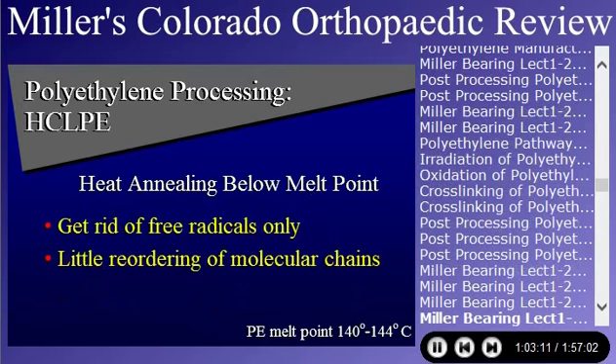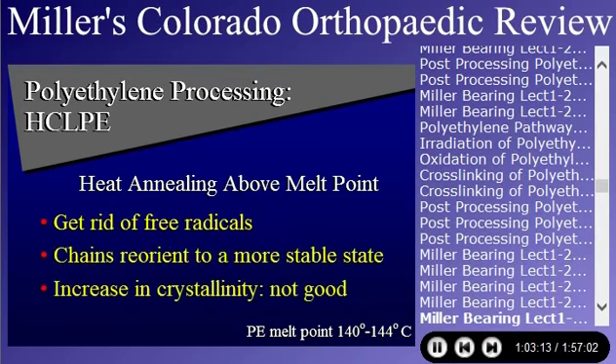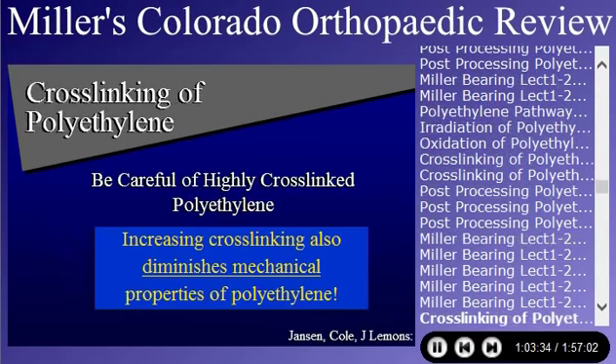The problem is, if you heat anneal above the melt point, you get rid of the free radicals, but the heating process also increases the crystallinity of the polyethylene, and you get more crystalline structure. Well, it's a more stable state, but guess what? It wears awful because you don't have those amorphous areas for cross-linking. So high cross-linking is good if you do it right. Isn't that a wonderful statement, huh? So you've got to be careful about highly cross-linked polyethylene.